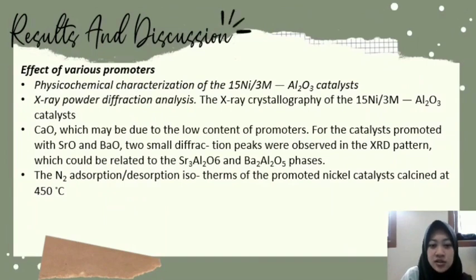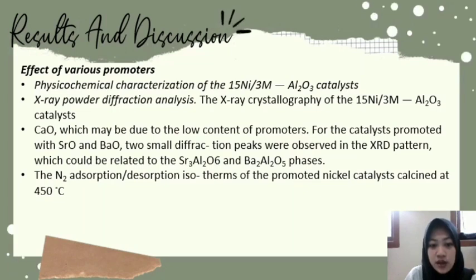Result and discussion. Effect of various promoters. Physicochemical characterization of the 15Ni/3M—Al2O3 catalyst. X-ray powder diffraction analysis. X-ray crystallography of the 15Ni/3M—Al2O3 catalyst. CaO, which may be due to the low content of promoter. For the catalyst promoted with SrO and BaO, two small diffraction peaks were observed in the XRD pattern. This could be related to the Sr3Al2O6 and Ba2Al2O5 phase.